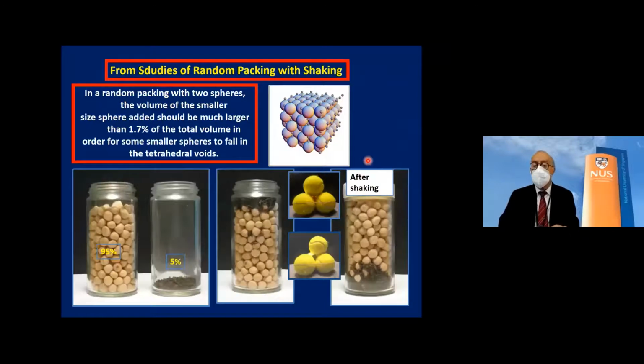Okay. But one thing, again, visual, is that, remember, I said, if you add the small spheres to the big spheres in this case, you add only 1.7%. But if you tried an experiment, like in this case, 95% these beans and 5% lentils, and you shake them together, you find that the lentils go down to the bottom. They don't go into the interstitial space. So what you have to do is something more.